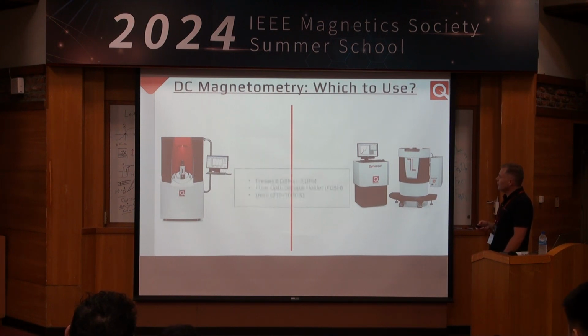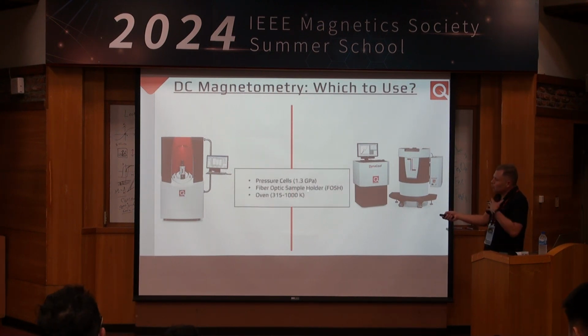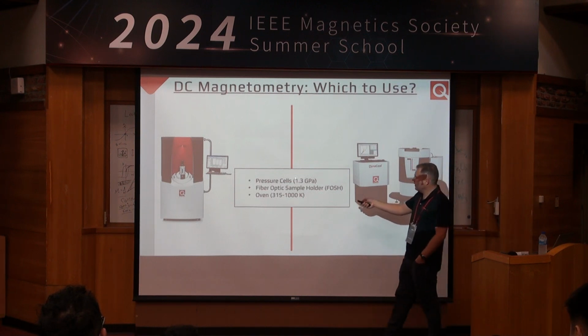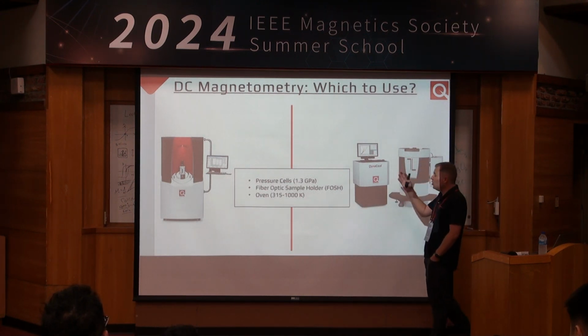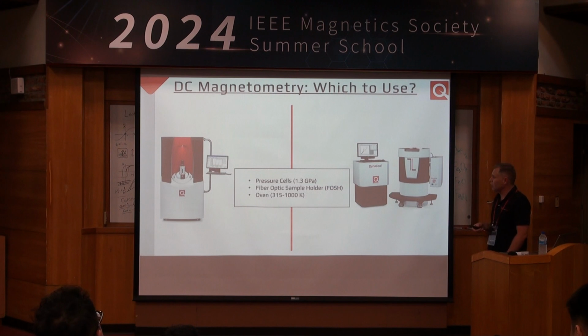Let's compare our systems, right? We've got the SQUID here, the MPMS3, and the VSM. Both of them can use pressure cells. We happen to sell hydrostatic pressure cells. They get you up to 1.3 gigapascals. You can put your own diamond anvil cells in here as well. We have ways to illuminate samples with light, and we have an oven option so you can measure up to 1,000 Kelvin. That's the same between the systems.